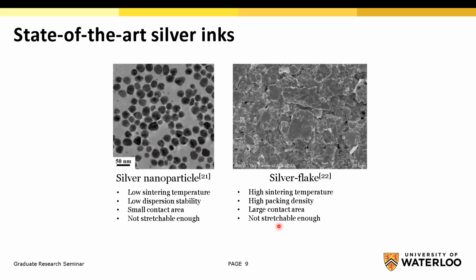and they are not stretchable enough. Another state-of-the-art silver ink uses silver flakes, and most commercial inks also use silver flakes because they are really low cost and really simple. You can see they have a much larger contact area. Flakes are in the micron scale, much larger than nanoparticles, which is why they have a high sintering temperature. They are much larger particles, up to 10 microns, and that's why they have a high packing density. They have a large contact area, which is better surface-to-surface contact and much better resistance,